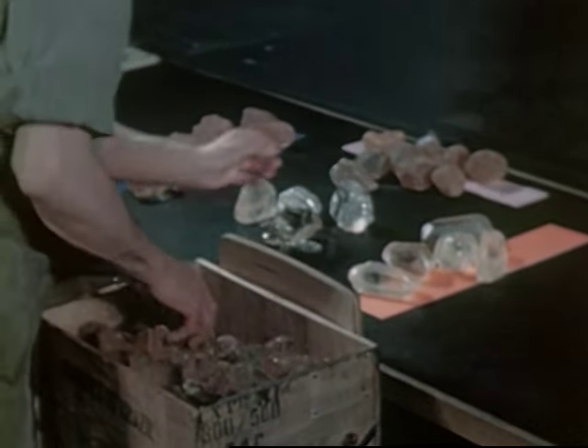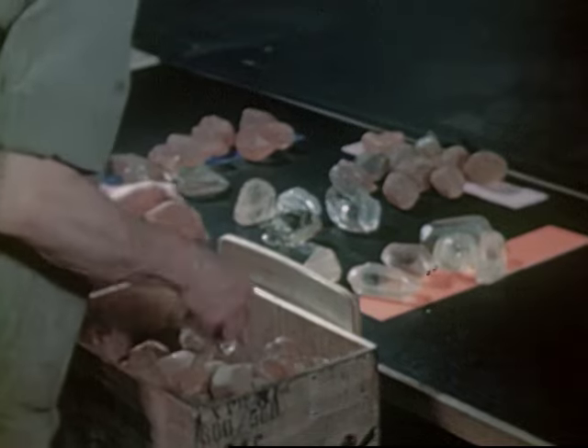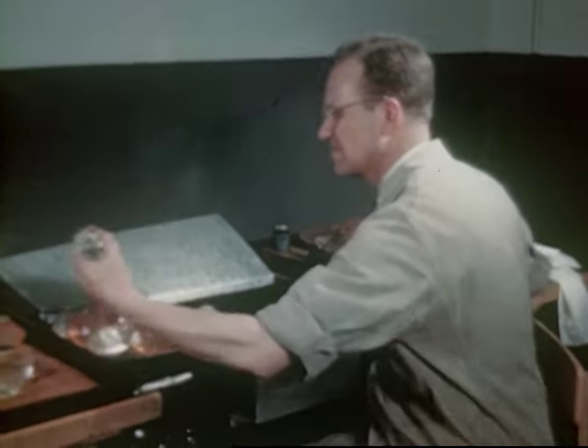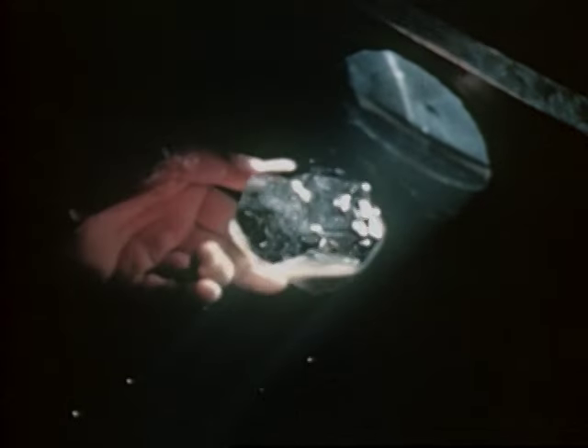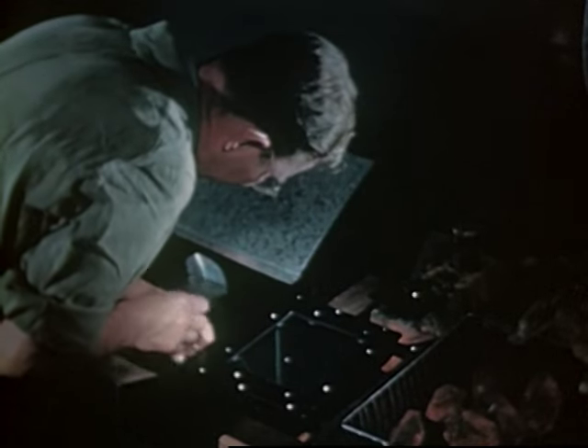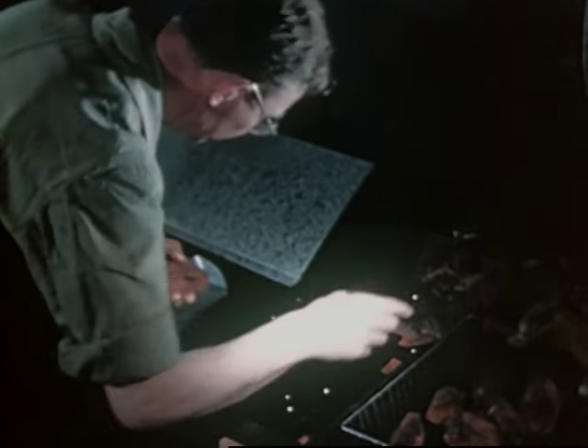After preliminary sorting, there is a thorough inspection for cracks, optical twinning, inclusions, and other internal imperfections. This is done in an immersion tank filled with a special type of mineral oil. The inspector submerges each quartz crystal and rotates it in a strong beam of light. Under oil, the surfaces of the quartz vanish, letting the interior imperfections come to light for the inspector to observe. From the character of these imperfections, he judges the usefulness of each piece. After the quartz has been examined under oil in polarized light, it is marked according to its quality.